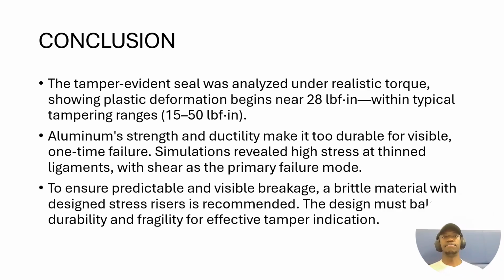In conclusion, this project simulated the tamper seal aluminium cap, and the tamper seal was analyzed under realistic torque, showing plastic deformation beginning near 28 pound-force inches, which is within the typical tampering ranges. To ensure predictable and visible breakage, I found that brittle materials with designed stress risers are recommended for a project like this, because if you use some other material, it could fail to break effectively, which could be inefficient for the design.